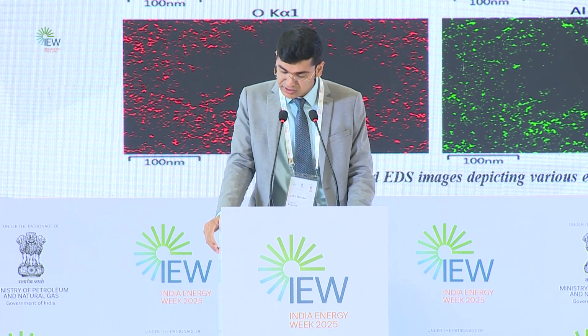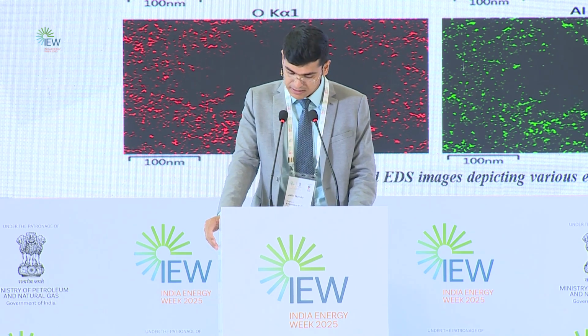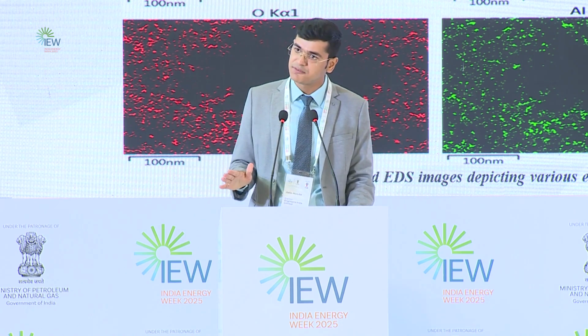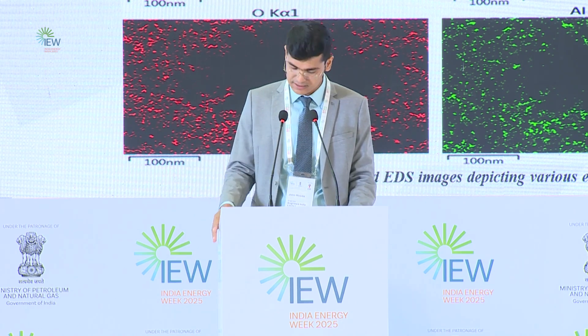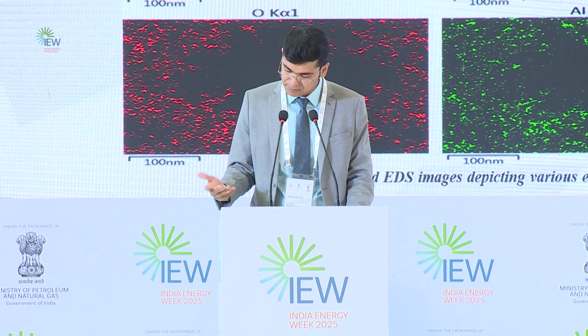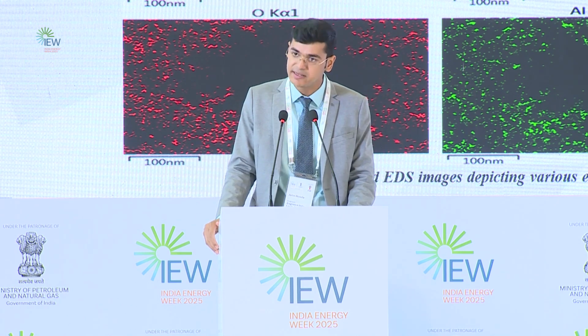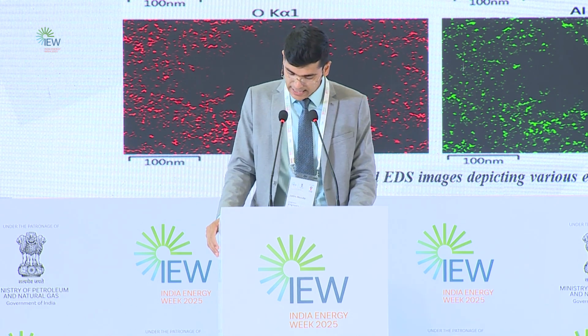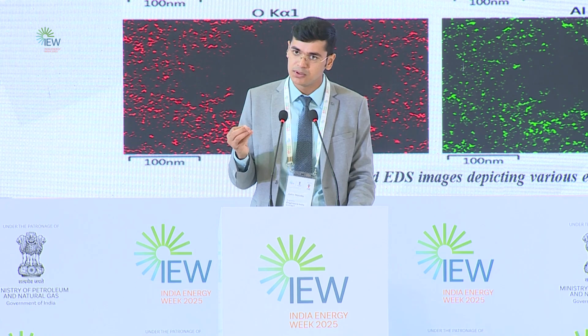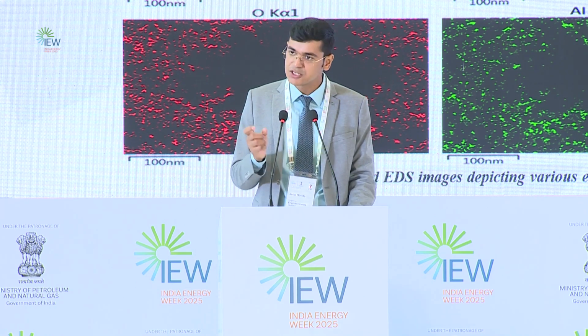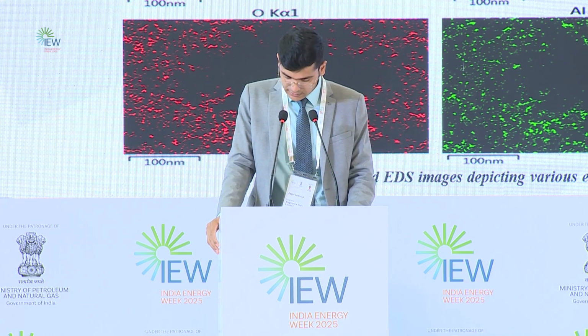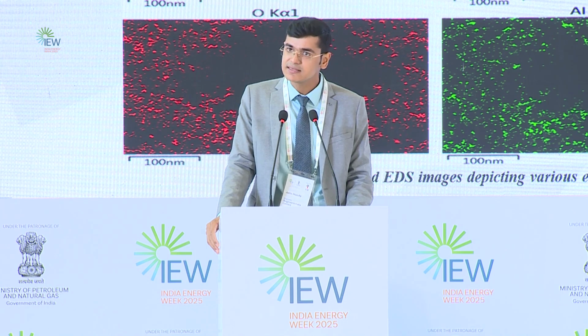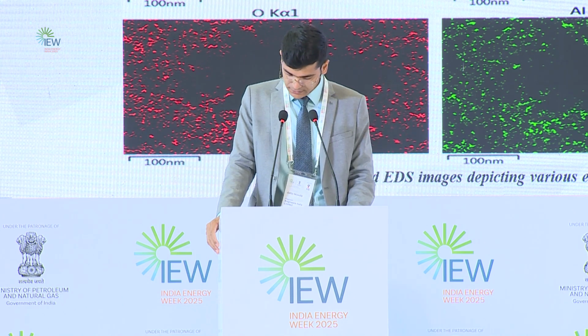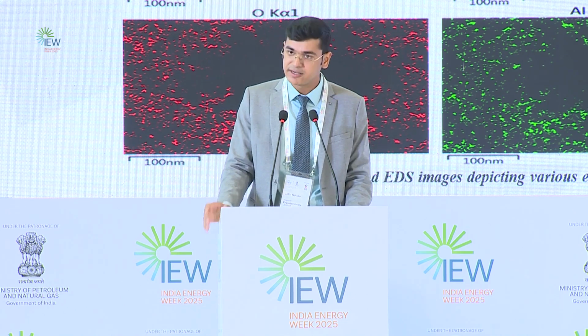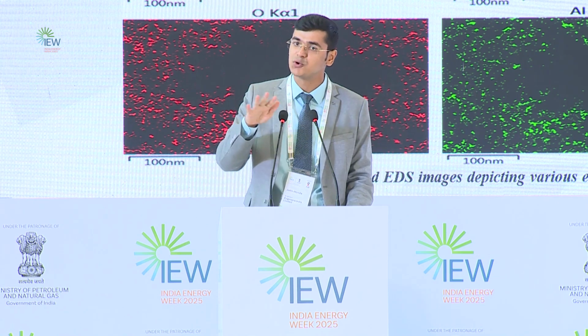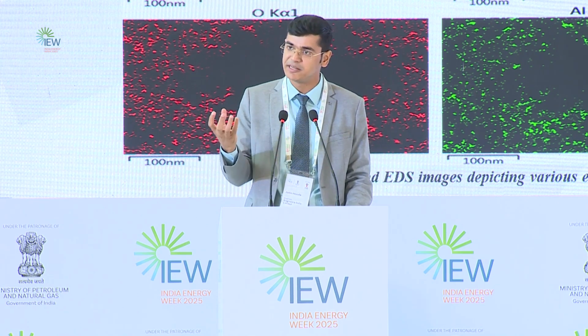Further, the detection limit in EDS depends on sample surface condition. Smoother the surface, lower the detection limits. And EDS can detect major element with concentration higher than 10% of the weight. And minor concentration it can also check out with a variation of 1 to 10% in weight. The detection limit for bulk materials is 0.1% of weight. Therefore, EDS cannot detect trace elements, but it can show you the composition of the material which has been tested.